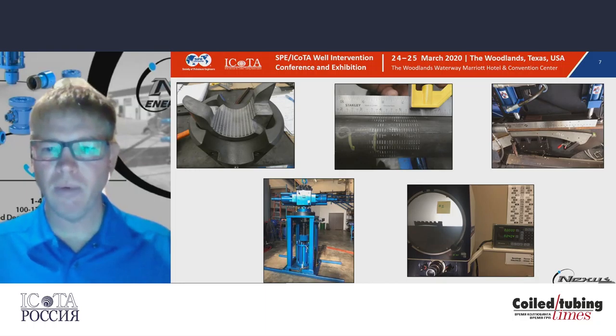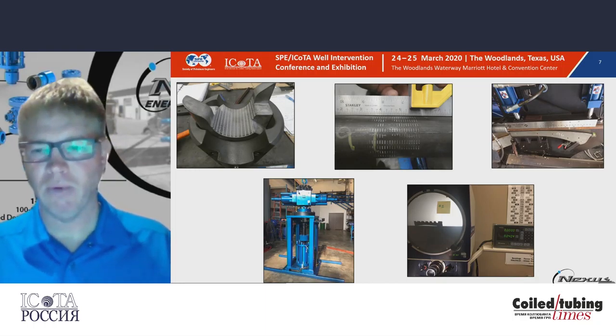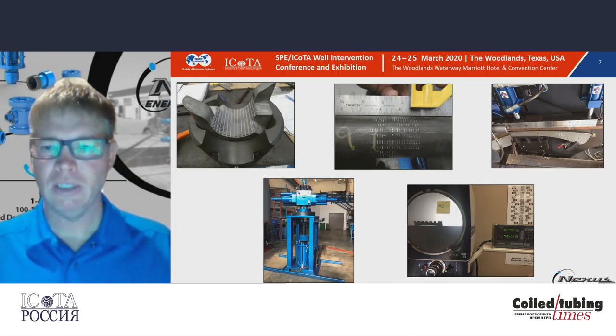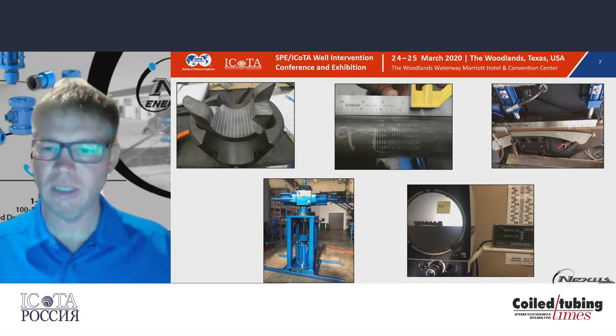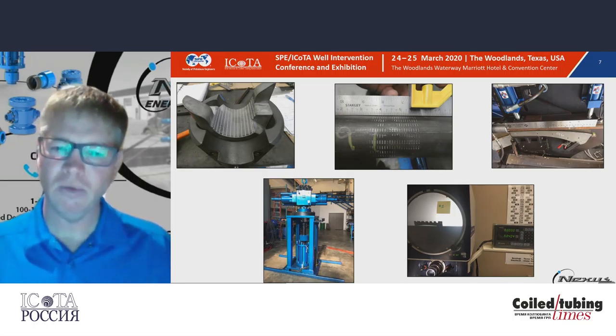The picture on the top right is my old bend fatigue machine from Trican. That's what we used for doing this testing. In that picture, you can't see it, that's an older picture I had, but we put the slip marks in the location on the bend fatigue machine where we expected the failure to take place. So we would put the most force possible.